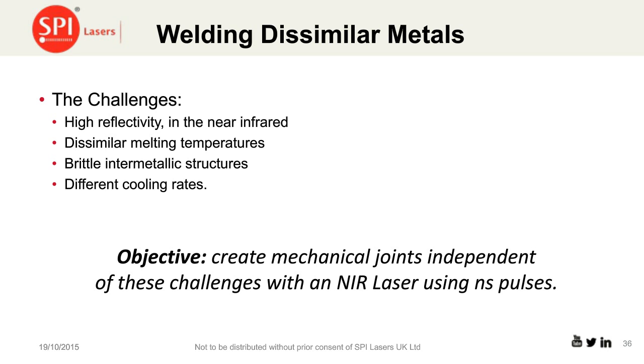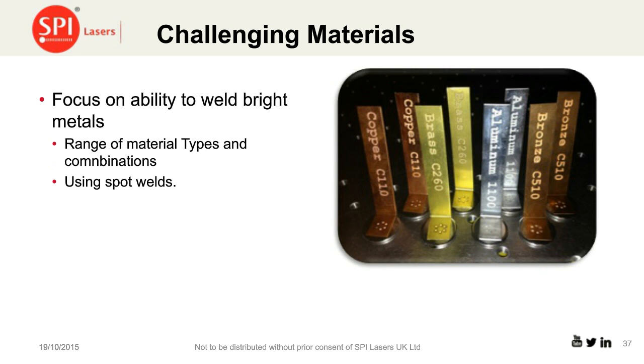The challenges are the high reflectivity in the near infrared, dissimilar melting temperature, brittle intermetallic structures, and different cooling rates. And the key here is to be able to create mechanical joints independent of these challenges with these 1 micron nanosecond pulses. Our focus is the ability to weld these bright metals in a range of material types and combinations. Our focus has primarily been on spot welds, although we do have some seam work as well.